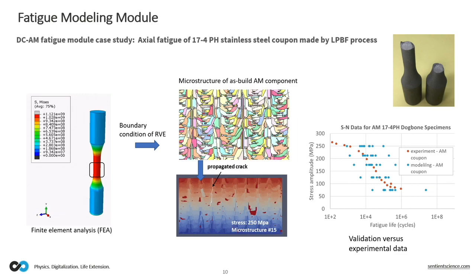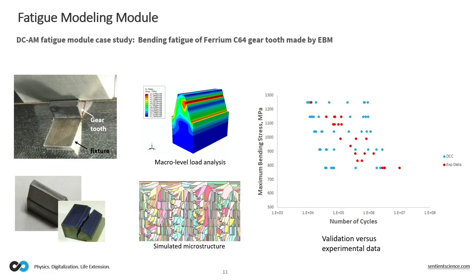However, if you go to a little bit more complex part, like this one, a single gear tooth, which is under gear tooth bending fatigue, now you can see that even the experimental data start to become wider because now we have more material, more possibility for the failure, so even the experimental data are wider than a simple dog bone. And again, this one was made from C64, which is a high strength aerospace grade steel. And again, we did the microstructure prediction, we did the fatigue testing, and you can see the comparison of our prediction versus the experimental data.